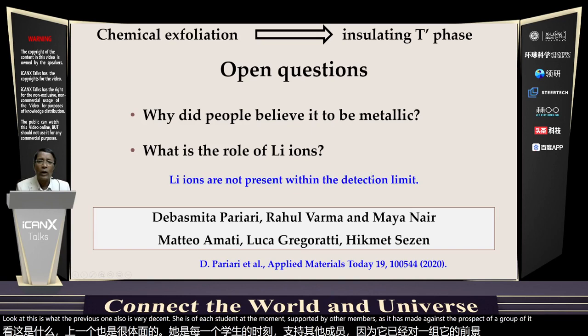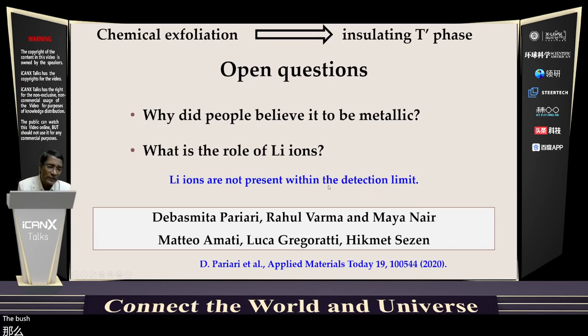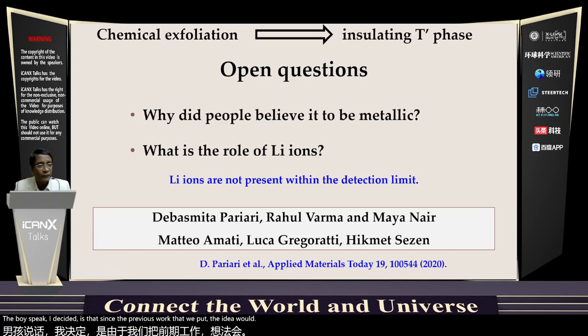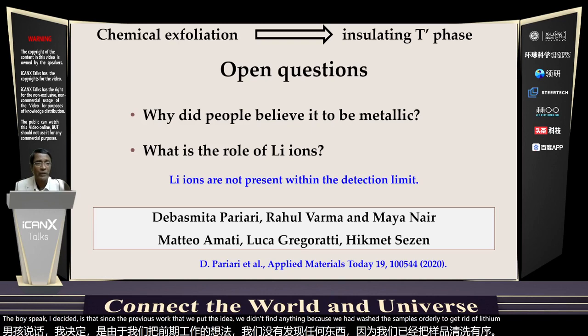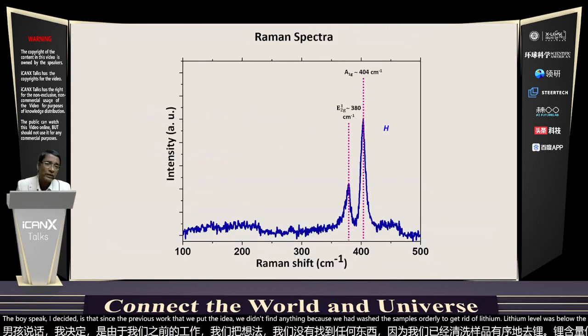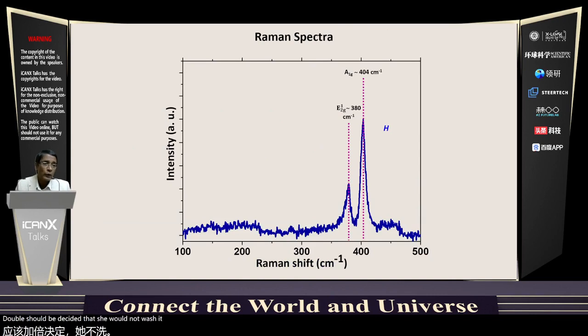So what Debasmita decided is that since in the previous work that we reported earlier, we didn't find any lithium because we had washed the sample thoroughly to get rid of lithium, the lithium level was below the detection level, she decided that she will not wash it. She will look at it with the lithium and try to see what is happening.